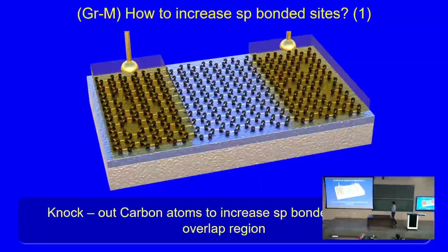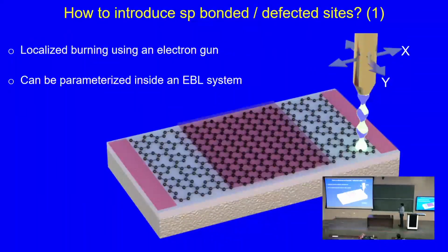So what we did, we basically came up with different ways of creating these sites. One was we used the electron beam to burn the local sites. You can use the same electron beam lithography tool, and you can even program where to create these burns. This happens in the region where you are going to deposit the contact. So you deposit PR, open the contact, then put it inside the litho stage again, program where to create the burn, take it out, clean, deposit metal, anneal, done.